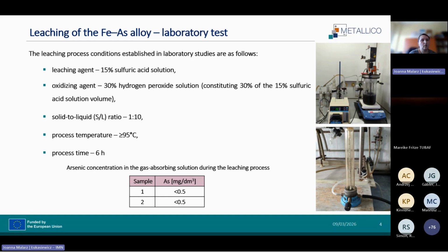You can see on this slide the leaching conditions. During the experiments, the arsenic concentration in the gas absorbing solution was measured to evaluate potential emission. In both tests, arsenic concentration didn't exceed 0.5 milligrams per cubic decimeter.